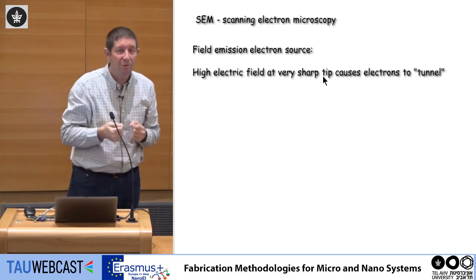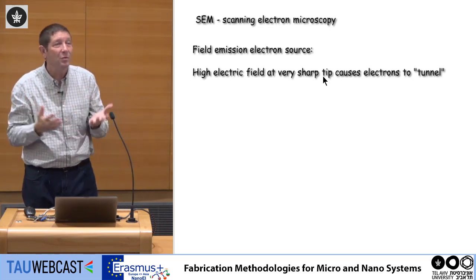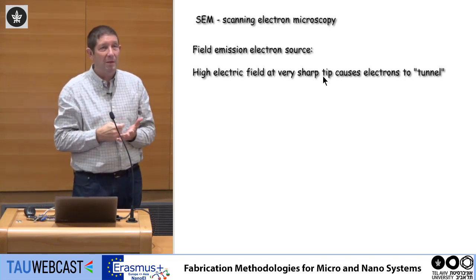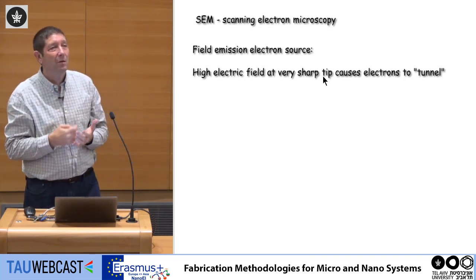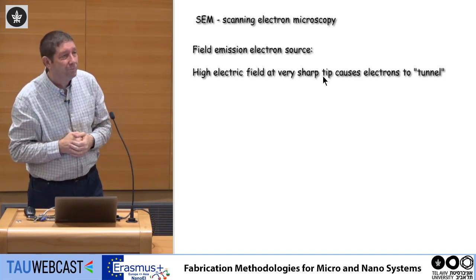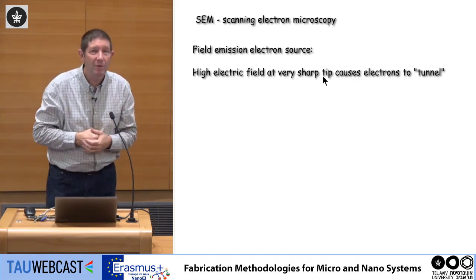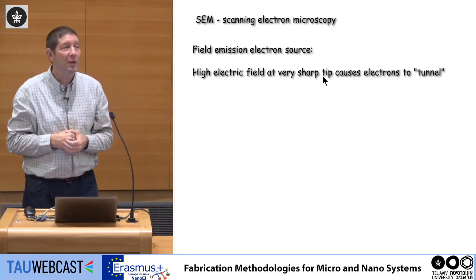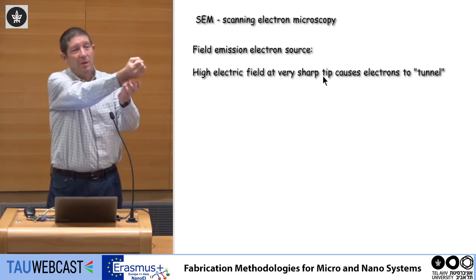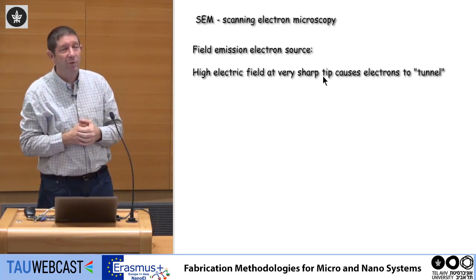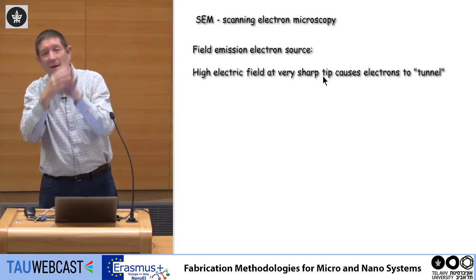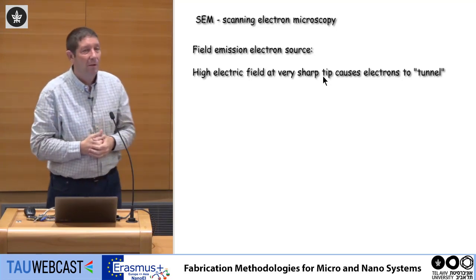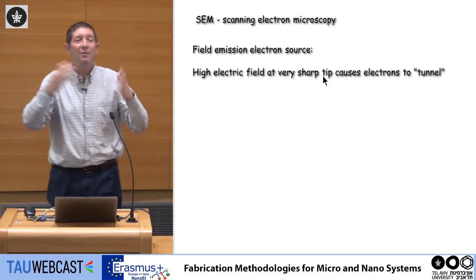So when the electric field reaches a value of about 10 to the 7 volt per centimeter, which is 10 million volt per centimeter, then you can have an effect which is called field emission. Because the electric field is so large, basically you can detach electrons from the surface of the material. They go via tunneling and are emitted. Now, you can say to me, oh, 10 to the 7 is a huge number.